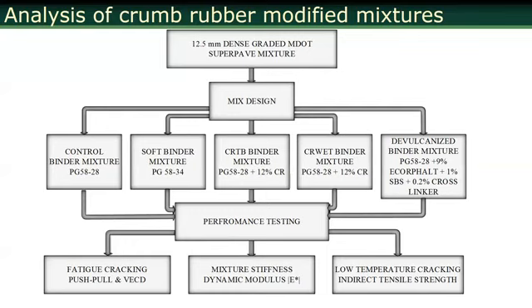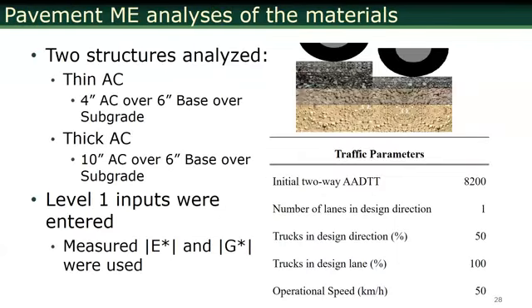This is a wet process mixture developed by ourselves, and this was a devulcanized rubber modified mixture that we've looked at. So we've done a whole bunch of testing for all these 5 different mixes. The idea was which one is going to perform better for a specific case. We had a certain structure in mind, and we looked at a thick structure and a thin structure.